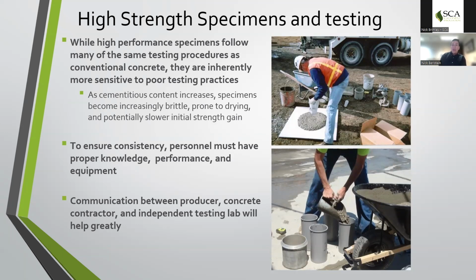In particular, if you get into high levels of SCM replacement, you have to be very cognizant of when you are going to move those cylinders and how they're going to be protected during that initial period, especially for thermal concerns when we have potentially 60 to 70% slag replacement. I always suggest having a conversation if you are going to differ from traditional ASTM specification and potentially leave cylinders to sit longer. That's generally a good idea, especially if that is in a well-controlled environment, just to make sure you are not damaging cylinders that might have lower than conventional concrete early strengths, which is a very real possibility.